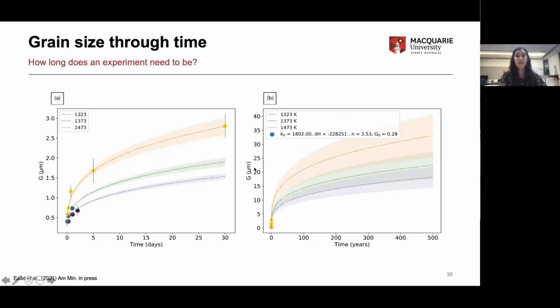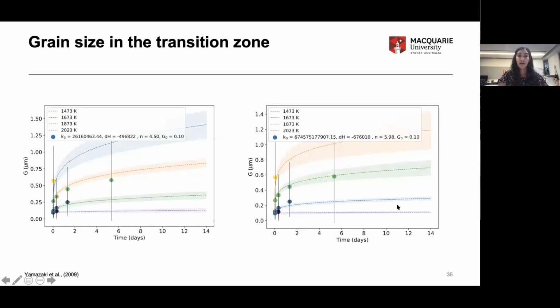And this problem isn't unique to Upper Mantle or indeed to the experiments that I did. I went back through the literature to try and see whether this problem existed throughout. And if we start to look at grain size in the transition zone, for example, previous work by Yamazaki et al. in 2009, they were also acutely aware of the problem of the grain growth exponent. So when they did their forward modeling, they fixed the grain growth exponent to the value they assumed it should be for the transition zone, 4.5, whereas the value they measured in their experiments was closer to 6. And again, the situation is the same.